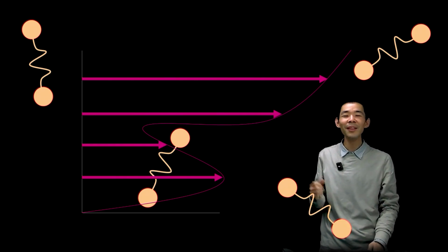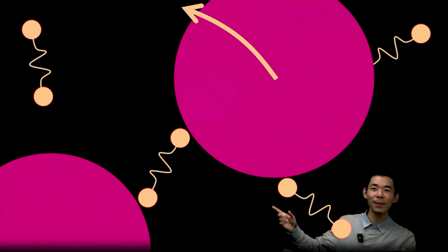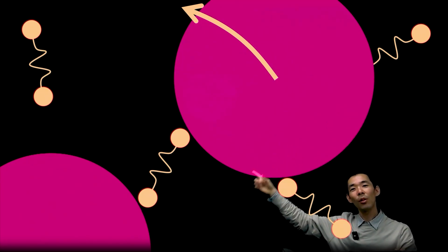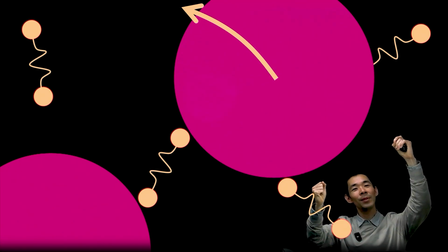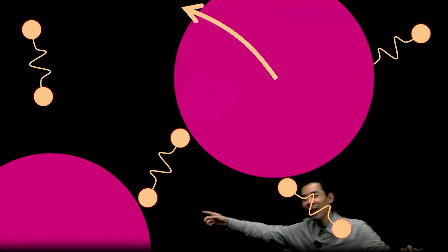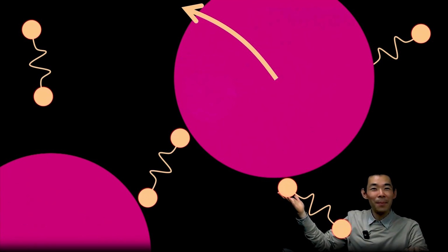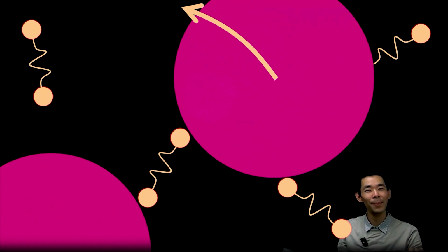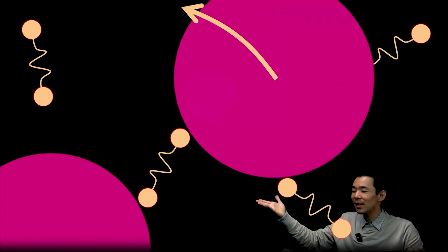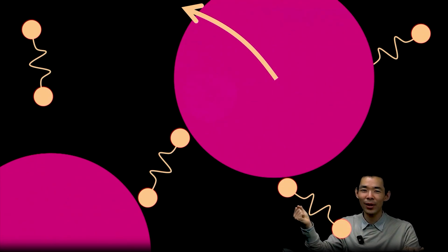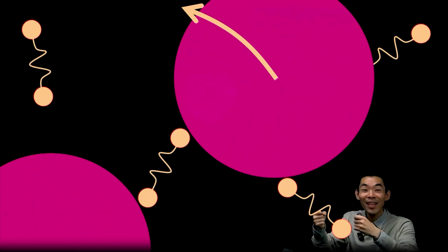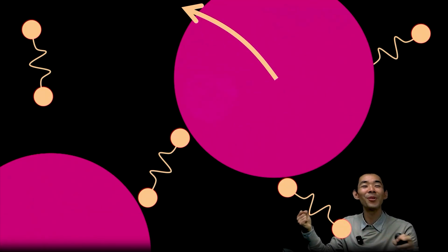Finally, for this particular experiment, what we see is that the colloidal separation distance is of the order of microns, but the chains themselves, the worms, are also of the order of microns. So you can have about a single chain that might traverse the entire interstitial gap. So there's a breakdown of the basic notion of the continuum approximation. We just don't have enough chains present in the interstitial region for us to have a continuum stress tensor at those points. And the interstitial region is where all the action's happening. So you want that region to be the most accurate.